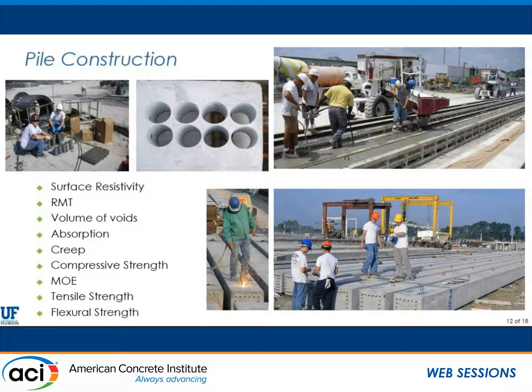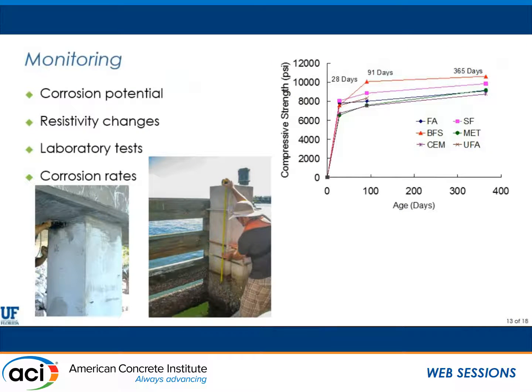As you might imagine, it was a bit of a coordination effort for us to make sure that when the piles were delivered to the contractor, they installed them in the place and in the orientation that we wanted them. Normally, the contractor's just grabbing the piles and throwing them into place, so we had to have the students mark the piles and make sure that we got them installed the right way up, so their sensors were in the right location. Our f'c for the piles was 6,000, which we got at 28 days, no problem. You can see some of the differences in the strengths there with the additions.